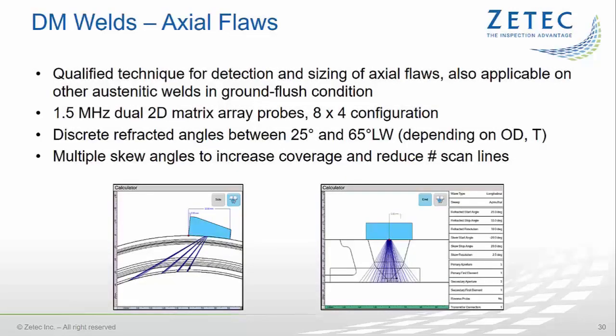Since the weld cap is ground flush, phased array probes can be scanned on the weld surface to inspect for axial flaws. Again, DMA probes at 1.5 MHz are used, but in this case, the probe assemblies are designed for sectorial scanning using the complete aperture of the probe. Typically, 8x4 matrix arrays will be used.